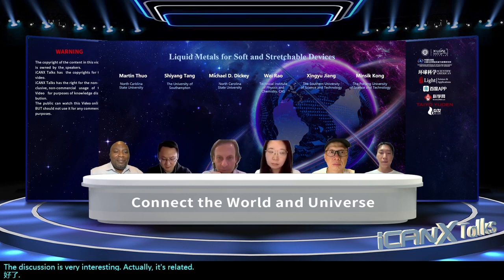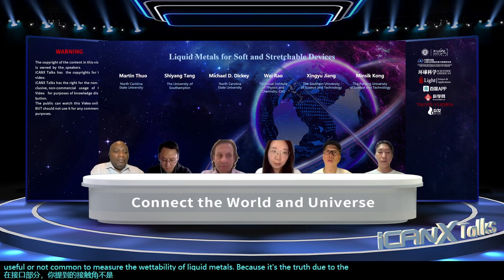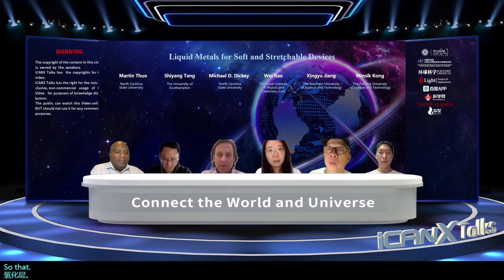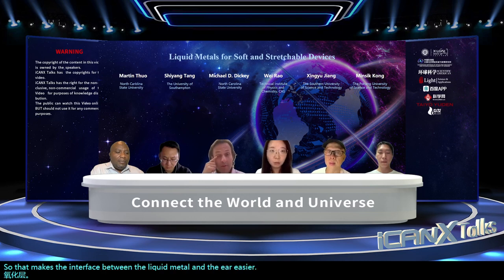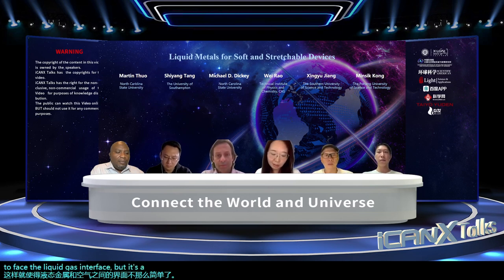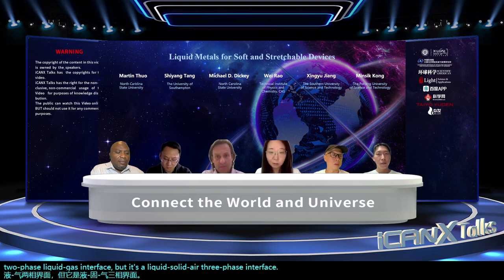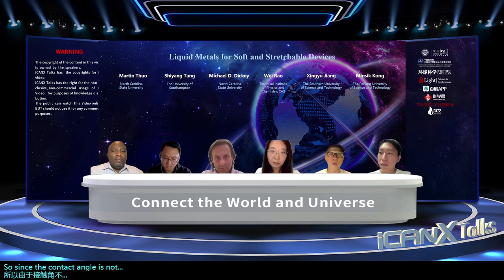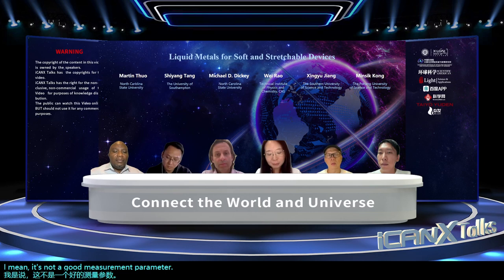Actually, it's related to some important problem of liquid metals. In the interface section, you mentioned the contact angle is not common to measure the wettability of liquid metals, because of the presence of the oxide layer. That makes the interface between the liquid metal and the air not a simple two-phase liquid-gas interface, but a liquid, solid, and air three-phase interface. So since the contact angle is not a good measurement parameter, I'm wondering, is there any better measurement parameter for the interface problem?